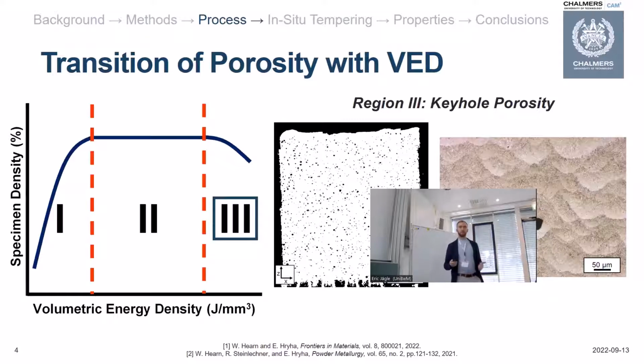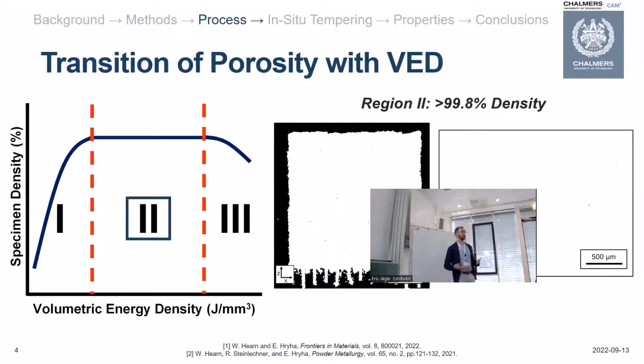And then finally, in between that, you have your sweet spot of the process window where you're able to make relatively pore-free specimens that have densities of 99.8% or greater. Now,